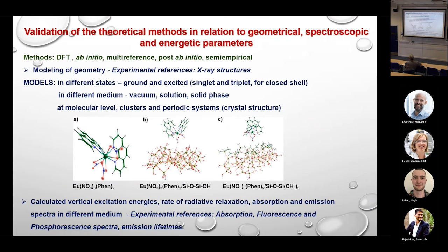So, the first step of our theoretical approach is to choose and validate the theoretical method, first in relation to the geometry. We use DFT, ab initio, multi-reference post-ab initio, semi-empirical methods. And we also perform different models approaching the experiment,